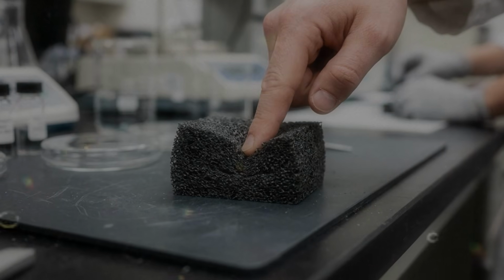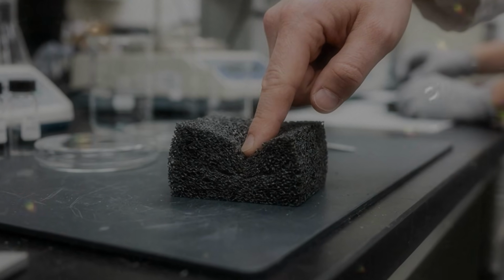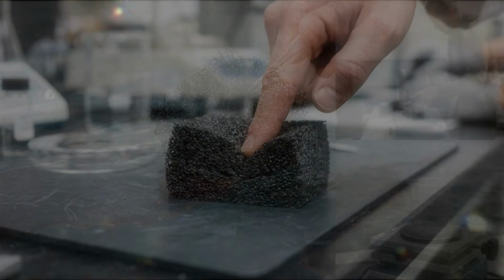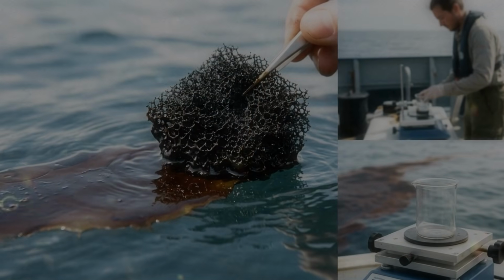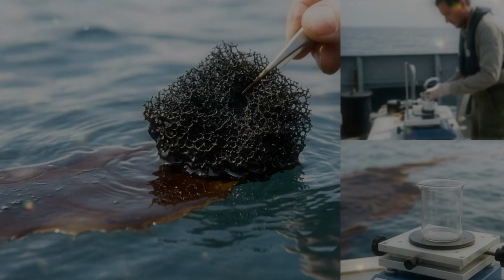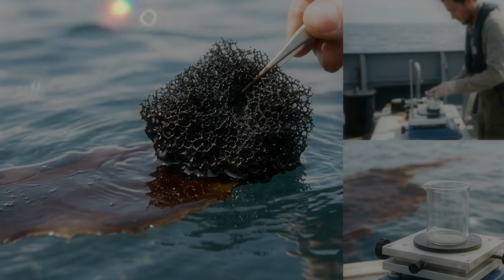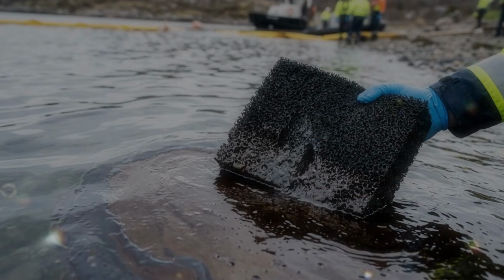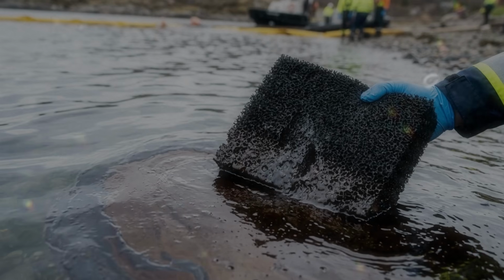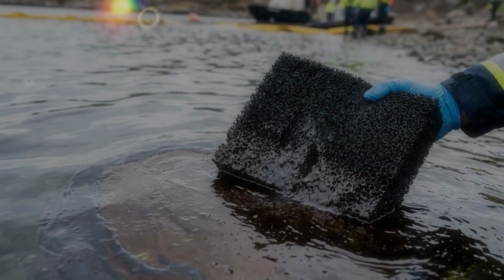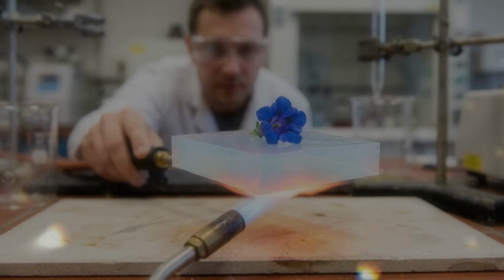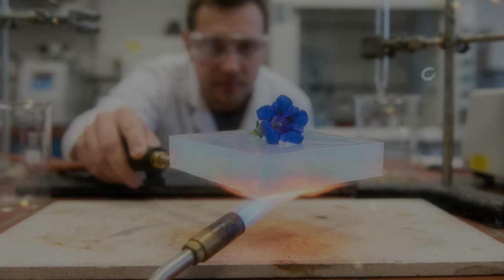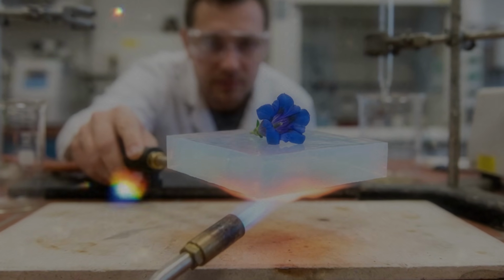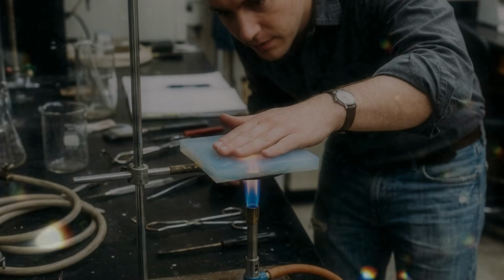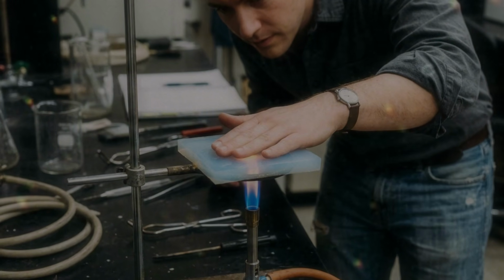Handling some aerogels requires care. Traditional silica aerogel can be brittle. Press a finger into a fragile sample, and the thin network may crack or crumble. Small particles can form on the surface, leaving a powdery feeling. Protective equipment may be appropriate in a laboratory or workshop, particularly when cutting or processing the material. The object may look like a harmless piece of cloud, but lungs are not improved by collecting clouds of fine dust.